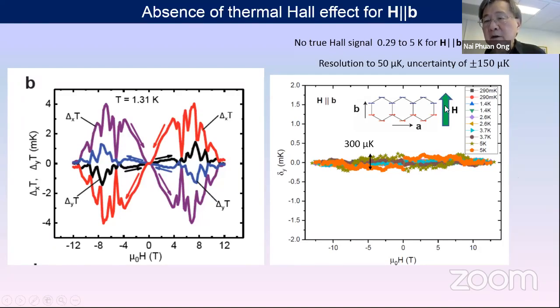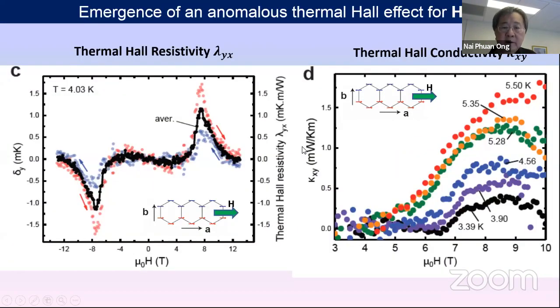No thermal Hall effect at all when the field is parallel to the armchair direction. However, in agreement with the Kyoto group, when we switch the alignment to the zigzag direction, initially at 1 Kelvin there's nothing. But at 4 Kelvin, you start to see the black curve appearing, a Hall signal. And this is very strange. The field is in plane, so there should be no Lorentz force. The system doesn't know what's right and what's left. Nonetheless, there is a thermal Hall signal, and it appears precisely where the quantum spin liquid is supposed to be.